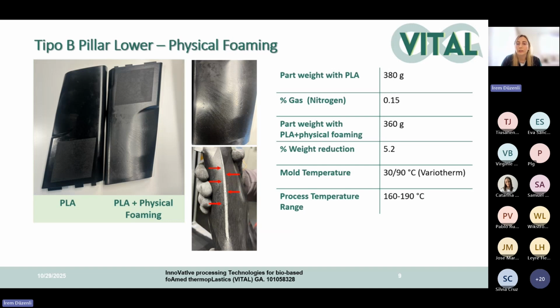In other parts, the type B pillar lower parts, we use physical foaming. And you can see the difference between PLA and PLA physical foaming parts. In these trials, we have some problems with surface defects because we need to keep air bubbles inside the parts, but sometimes they occur on the surface. So we need to get rid of these problems. In our first case, we use Variotherm, a fast heating and cooling system. We believe that if we work efficiently with Variotherm in our trials, we can minimize these kinds of problems on the surface because of the fast heating and cooling system.